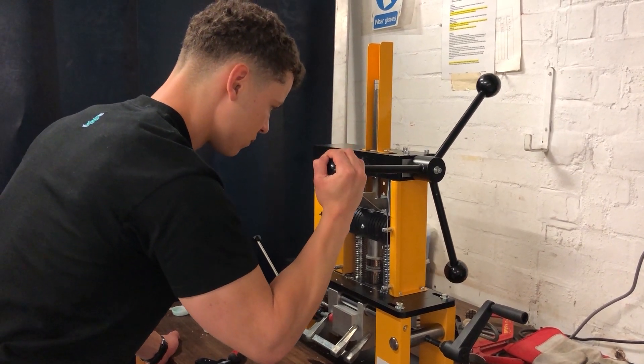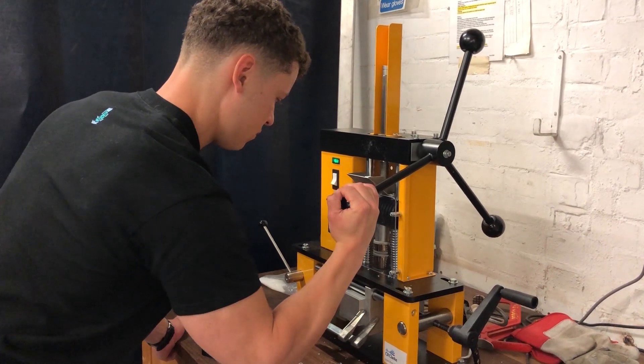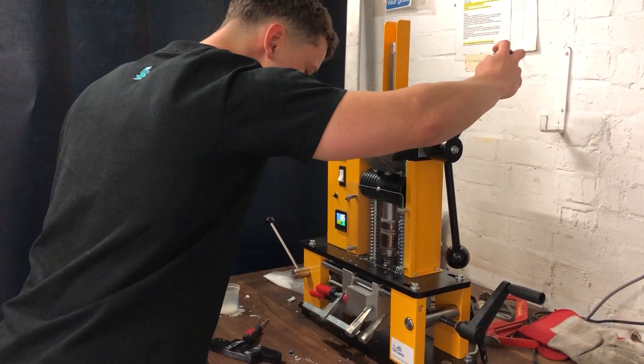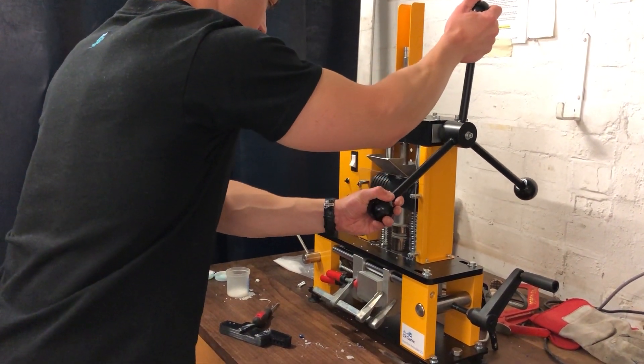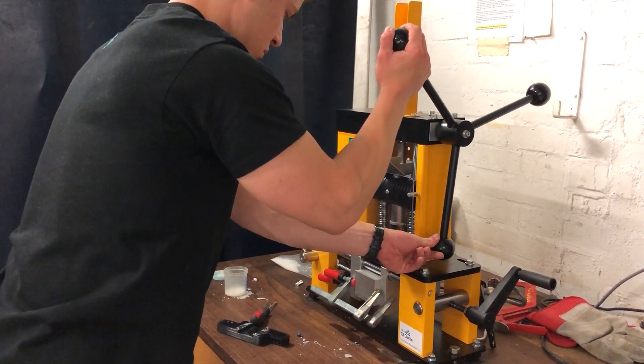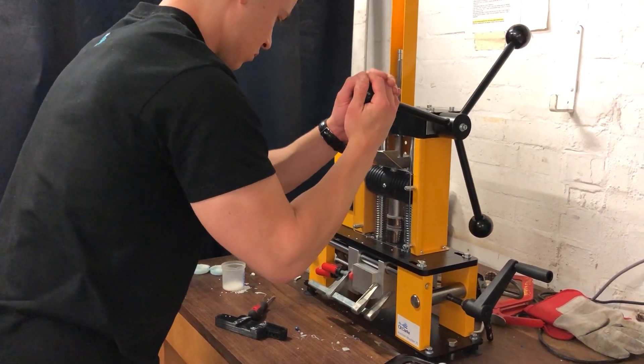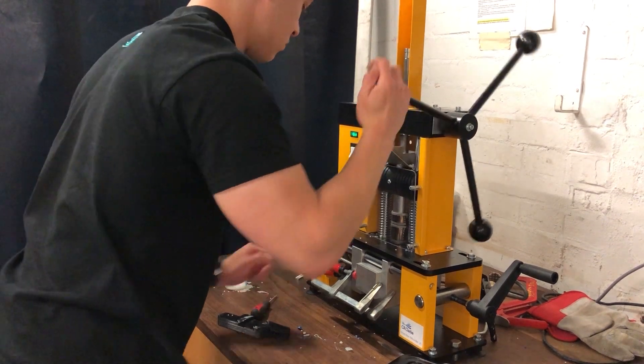The largest technical difficulty faced throughout the project was experimenting with different 3D printing materials for the mold and finding the correct temperature for the molder to produce a repeatable process with good quality parts. I experimented with different combinations of ABS, PETG, PLA, and resin for the mold material, and PLA, ABS, and polymorph pellets for the injected polymer, with temperatures ranging between 160 and 200 degrees Celsius on a CR Clark injection molder. I found the best combination to be PLA pellets injected into PETG molds at 190 degrees Celsius.